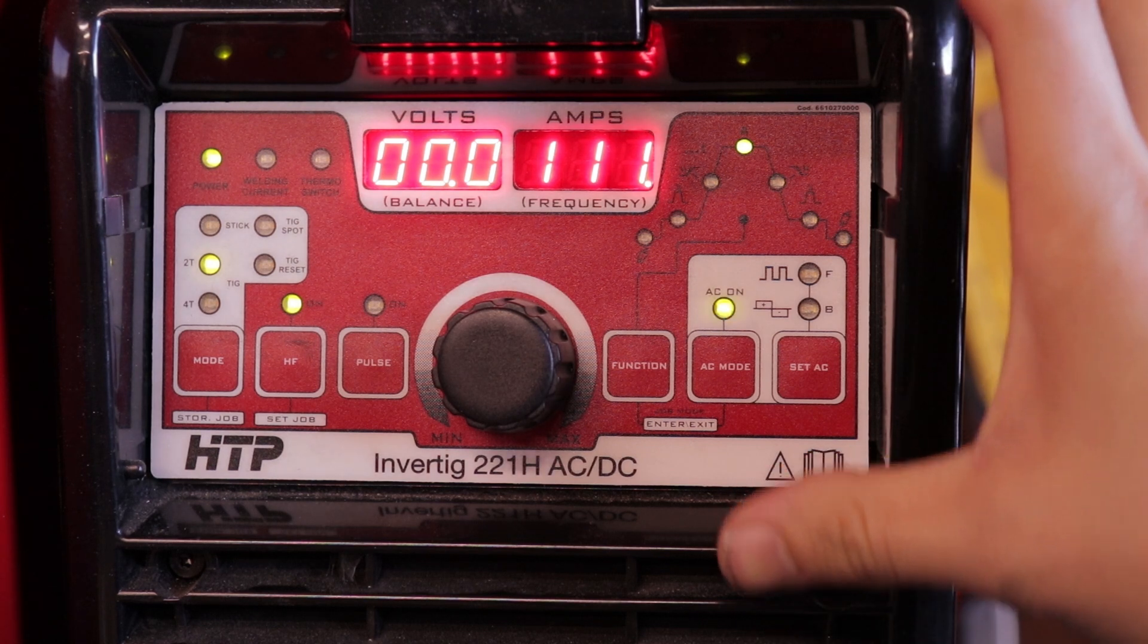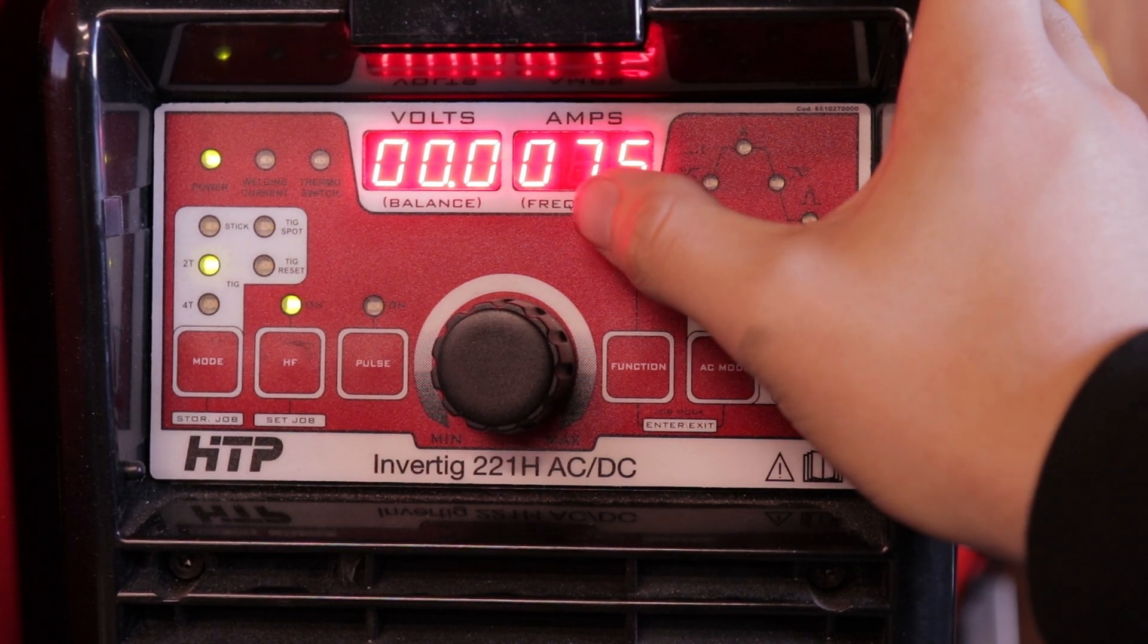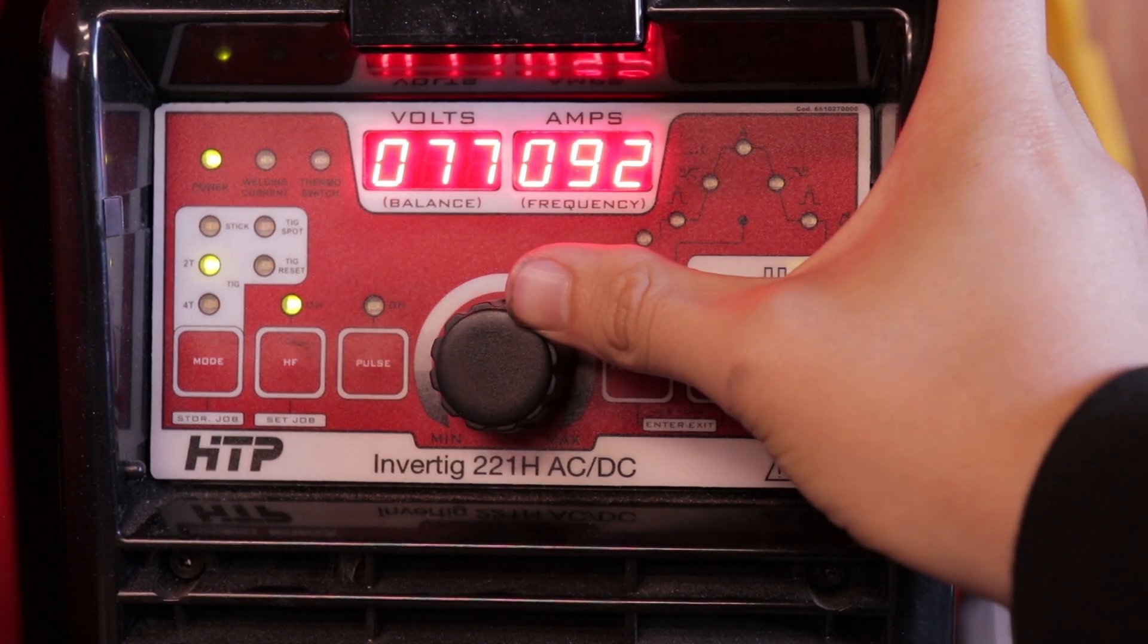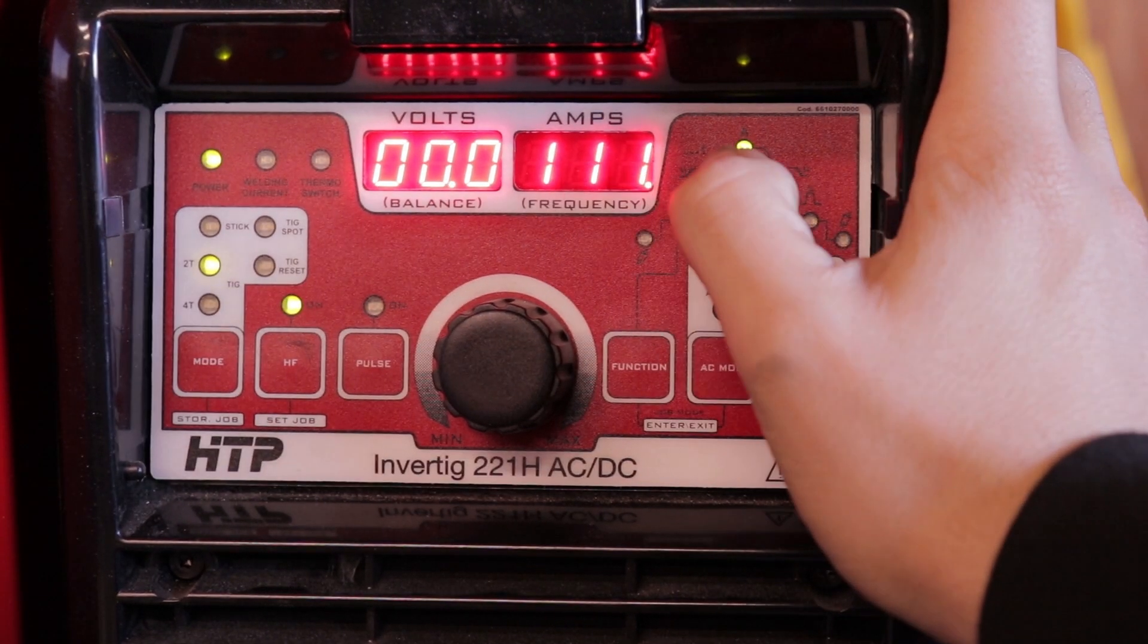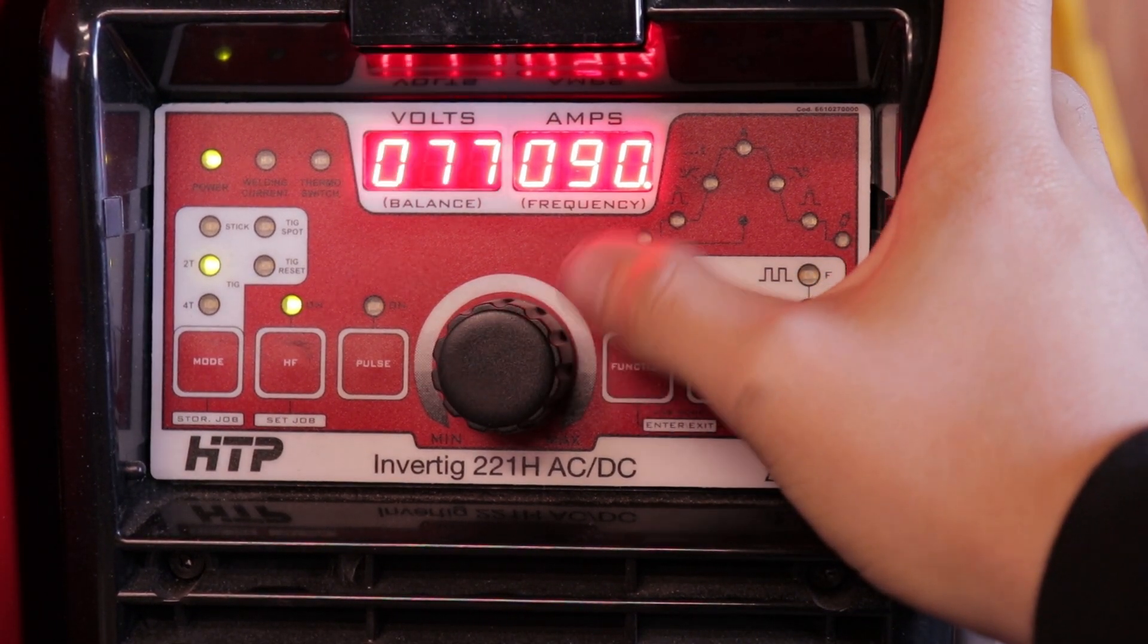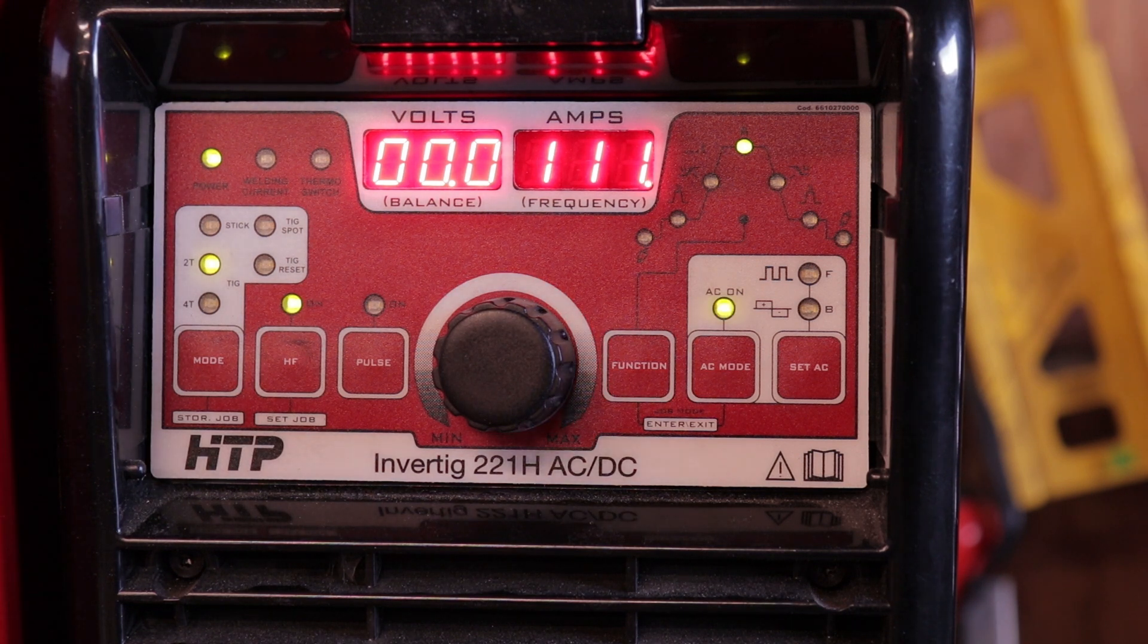For the 16 gauge aluminum that we're doing, I'm on AC. I've got my electrode positive down to 75. I actually wanted my frequency at 90 but the first one that I filmed that's in this video is actually at 200 hertz. But I like 90 more for outside corners. And then my balance is at 77. No pulse, 111 amps, and that's going to give me enough to play with because I'm really only going to be around 80 amps probably since it's 063 material.